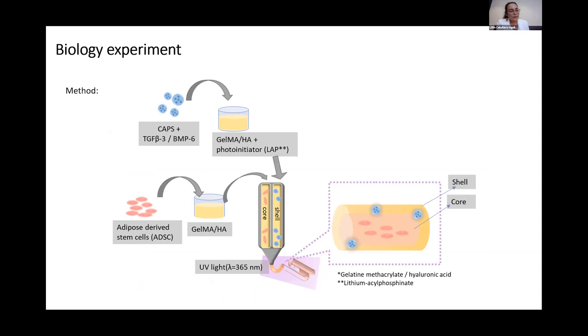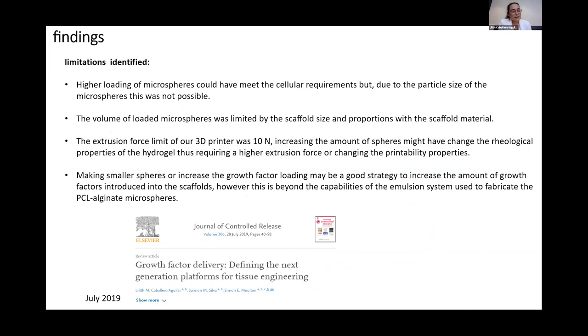So I used my microparticles to encapsulate TGF-beta3 and BMP6. And we mixed that with GelMA and hyaluronic acid at the time. And we printed that and then we waited for 21 days to see if we could have some differentiation, but that actually didn't happen. Thanks to that experiment, we were able to identify a lot of the limitations that the system had. So basically the microparticles were slightly too big to fit within the scaffold size that we were aiming for. Also, the loading wasn't the best. If we wanted to load more growth factors, we needed to increase the amount of particles, and that was not really possible. So we ended up with the conclusion that making smaller spheres and increasing the growth factor loading was the way to tackle this issue.